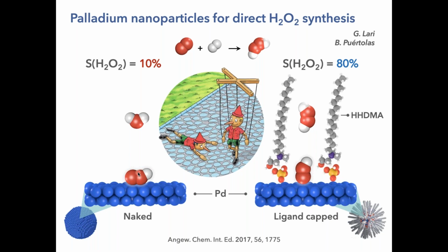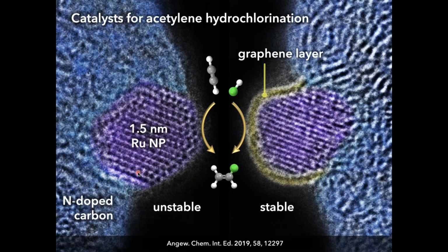So that's how you can also use nanostructuring to design new catalysts and new reactivities. And that's another beautiful example of how a nanoparticle of ruthenium that is very unstable in acetylene hydrochlorination because of redispersion effects can be made much more stable by an order of magnitude by attaching a graphene layer on the surface, just one layer of graphene, one atom of carbon thick, which embeds the nanoparticle and decreases the kinetics of dissolution and redispersion of the nanoparticle.